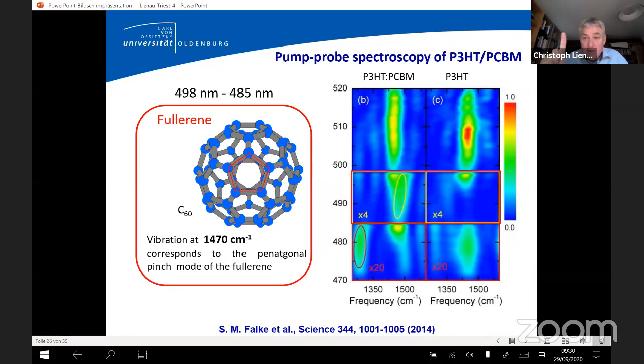So what is happening here is we excite the polymer, but it's not only the polymer that starts to vibrate, but it's also the C60 that coherently starts to vibrate. And that can only happen if there is a flow of charge from the polymer to the C60 within less than half a vibrational period. Because basically we need to impulsively or coherently excite the vibrational modes. And so there must be some extremely rapid coupling. And this coupling cannot just be a hopping within a few femtoseconds of the charges, because this would not explain the spectra. There must be an extremely strong coupling between the P3HT excited state and the C60 lowest unoccupied molecular orbital, to explain those observations.